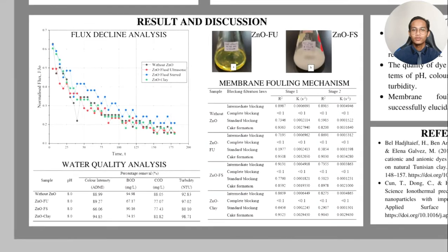Now, we are moving on to results and discussion. For synthesis of ZnO fluid, based on the findings, synthesis of ZnO fluid with two dispersion methods was successfully done. The result shows the sonication of ZnO fluid produces a semi-clear yellow fluid and suspended solids were hardly seen in the fluid. On the other hand, stirred ZnO fluid shows the expected result of white cloudy fluid. This result may be caused by the heat generated by the sonication process, which cannot be controlled.